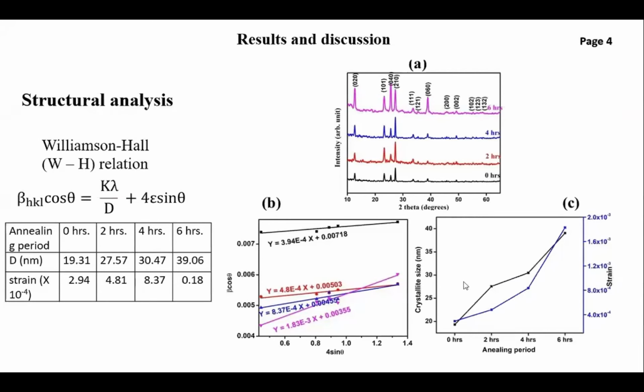Also, we used the Williamson-Hall relation to calculate the crystallite size as well as strain. The equation used here is beta cos theta equals K lambda over D plus 4 epsilon sin theta. So by comparing this equation with the equation of a straight line, the value of D, which is the crystallite size, and epsilon, which is the strain, can be determined. Now, the values of D and epsilon are tabulated in the table, and also presented graphically in figure 1C. As we can observe, the D value increases with increasing annealing period, having values of 19.3 nanometers up to 39.06 nanometers. Meanwhile, the strain increases with increasing crystallite size. But at 6 hours, the strain starts to decrease to a value of 0.18.